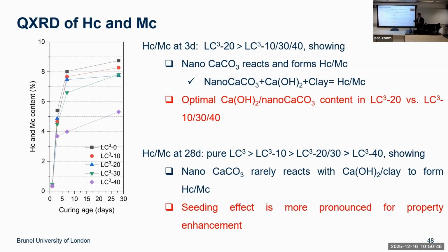In other words, we see that this nano calcium carbonate has 3 functions. One is seeding, nucleation, one is filling, and the third one is the carbonation reaction, still in the aluminum phase. So the research shows that the nucleation effect is more pronounced for this technology.